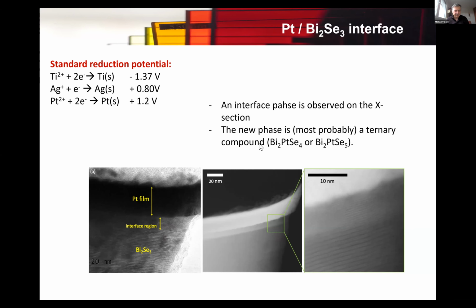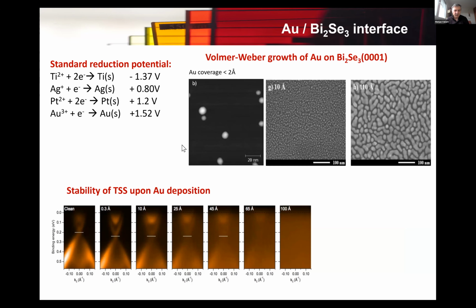And finally, then we said, let's go to our champion of the noble metals, and that is, of course, gold. And we repeated the exercise. We deposited gold on the surface of bismuth selenide. So you get such clusters of gold when you start doing that, which then get more densely populated, and then they even merge into such a structure that you see here.